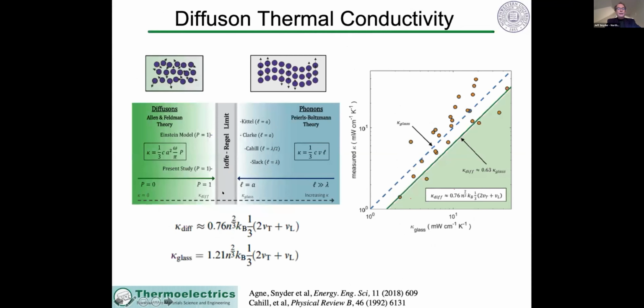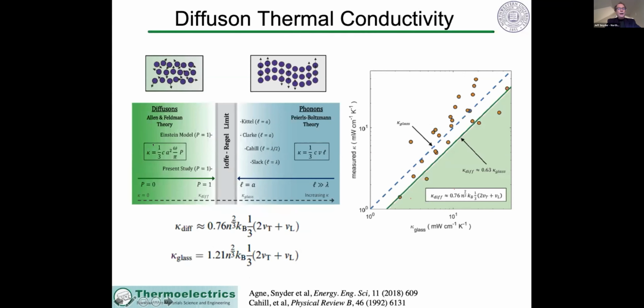So the way we like to think about diffusons is that it's diffusive transport, as opposed to the traditional phonon method with thinking about a velocity and a mean free path, whereas diffusive transport, we need a diffusivity where we think about the attempt frequency to go 1 unit of distance, so that's the a squared term, and then you have a probability.